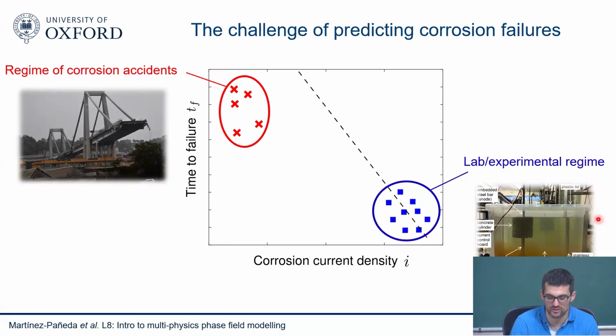This is what we do. So this is our impressed corrosion current test. This is an example of a classic accelerated corrosion test. You basically enhance or maximize the severity of the corrosion process. For example, you run your test at very high corrosion current densities, and therefore you get corrosion happening much earlier. But then you need to extrapolate all the way from here to here, and it seems that we keep overestimating when corrosion will happen, because it's a big extrapolation that we have to do there.